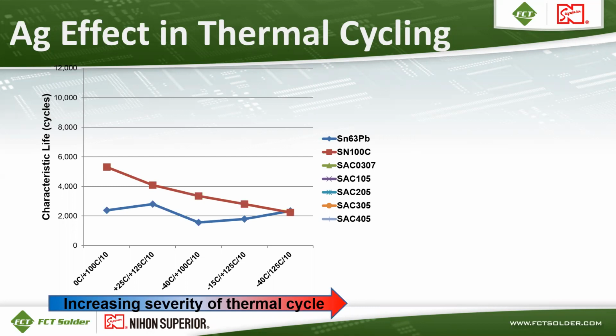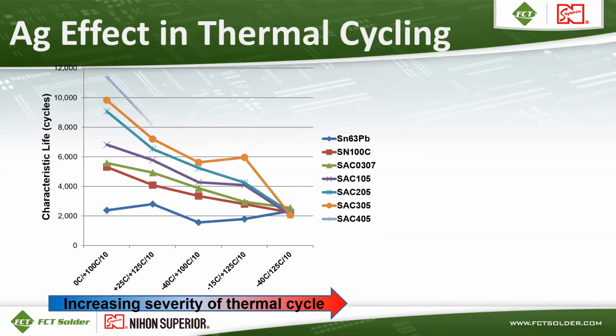SN100C alloy decreases in characteristic life as you go from less aggressive to more aggressive thermal cycle tests. The same is true of SAC 0307, which pretty closely mimics SN100C. Then you've got SAC 105, which follows the same trend. SAC 205, 305, and SAC 405 all follow the same trend. One thing you'll note, though, is that as you increase silver content with a temperature range of 0 to 100 C for thermal cycling, the characteristic life is much higher.